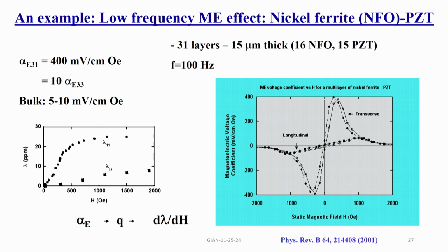We put together a multi-layer of nickel ferrite and PZT, and this one had 16 layers of nickel ferrite, 15 layers of PZT, so the total is 31 layers. Each layer is 15 micron in thickness. We made these ferrite and PZT by what's called tape casting. It's a lengthy process. In tape casting you make these layers separately, the ferrite and PZT. Then you stack them up the way you want, in sequence, nickel ferrite, PZT, nickel ferrite, PZT. So you build this multi-layer, then you can press it in a hydraulic press, then you can sinter it at high temperature. Then what you get is a pretty good multi-layer sample, and that's what we had.